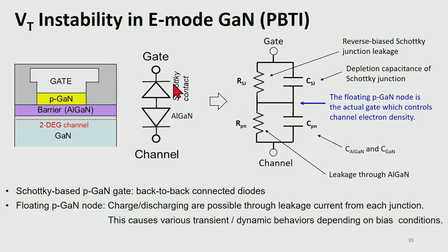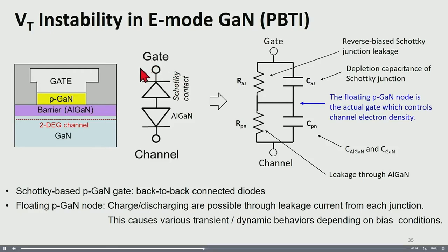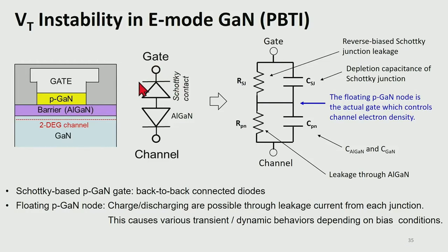Now we can move to the threshold voltage instability in the E-mode device. The E-mode device gate structure is a little more complex than the D-mode. Especially when the gate metal forms a Schottky contact to the P-GaN, the gate structure is like back-to-back connected diodes. And this can be modeled as a series and parallel connection of voltage-dependent resistors and capacitors. In the case of the top junction, it's a reverse bias Schottky junction. So the resistance is determined by the reverse bias leakage current in this top Schottky junction, and the capacitance is the top P-GaN depletion capacitance.